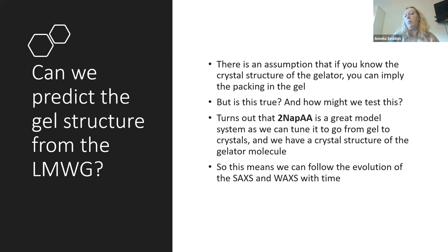So what we can do is follow the evolution of the gel state with small angle scattering, and follow the evolution of the crystal state with wide angle scattering. Wide angle scattering is simply looking at molecular level organization, rather akin to powder X-ray diffraction, but now we're doing it in solution rather than in a powder pattern.